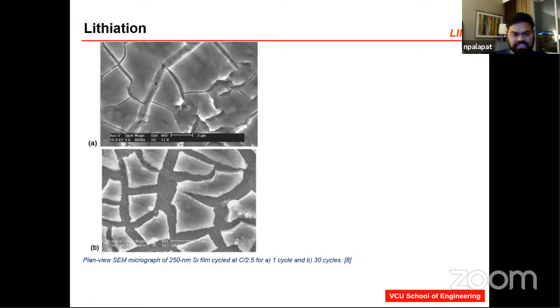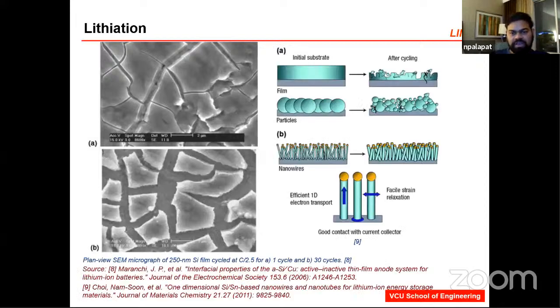As you see, some of the material lost contact with the surface area, thereby the output of the battery reduced eventually after 30 cycles. And this is how we can visualize it on nanowires. So nanowires, when you carefully design them, grow in specific directions, and when they undergo these lithiation procedures, it is known that they can withstand better and they can grow in a particular direction, providing a known strength of the material.